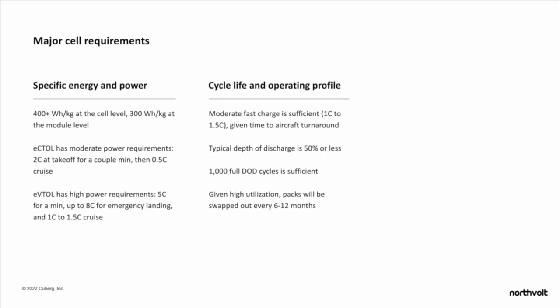Cycle life as well, everyone wants more cycles. But I would say about 1,000 full depth of discharge normalized cycles is sufficient for many of the early applications. This is going to be both a cycle life and cost parameter. But cycle life is important, even setting aside unit economics, because the packs are utilized to such a high degree. You're basically trying to fly these aircraft continuously as much as possible and with very demanding profiles. So estimates are every 6 to 12 months, these packs will need to be swapped out from the aircraft for new packs. And this actually has quite a few implications, both in terms of module and system design, as well as in what kinds of capabilities and business models from a battery provider really make sense to serve these use cases.